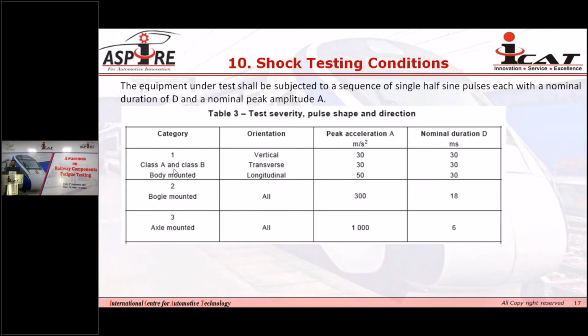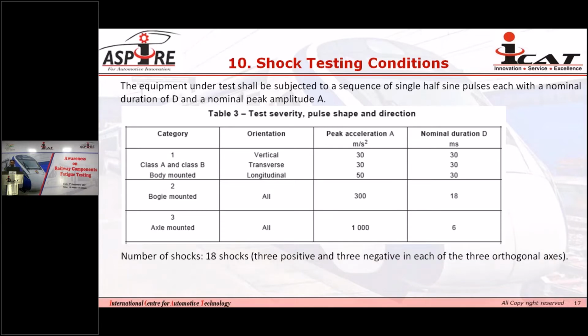If we refer to category 1 class A and class B body mounted, you will find the same acceleration level and nominal duration for category 1 class A and class B. Along the vertical direction it is 30, transverse 30, and longitudinal 50 meter per second square. This is the acceleration level, and this is the pulse duration, and the wave shape will be half sine. The total number of pulses to be generated along each direction will be 18 shocks. This means 3 positive shocks and 3 negative shocks along each direction, so 6 pulses along the vertical, 6 along the transverse, and 6 along the longitudinal axis.